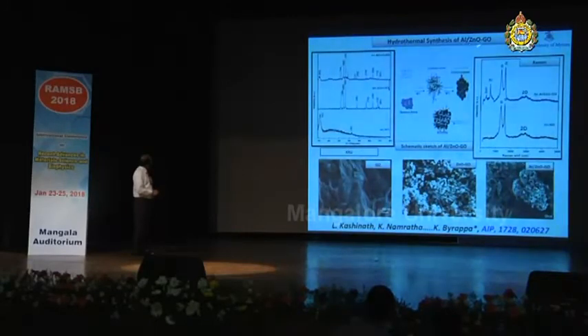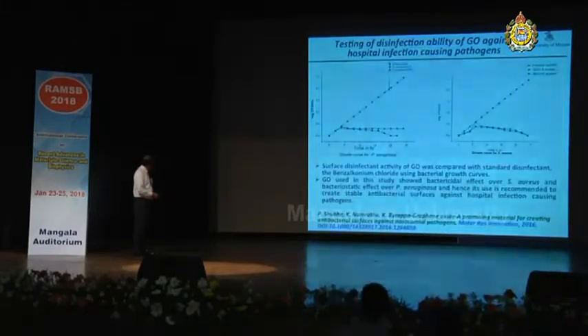And we have further added aluminum into the zinc oxide and graphene oxide composite, and these are the X-ray diffraction patterns and the Raman shift noticed, and the characteristic images, SEM images, FESEM images.